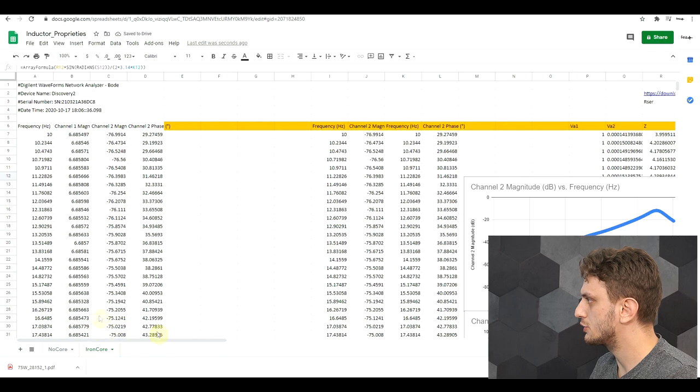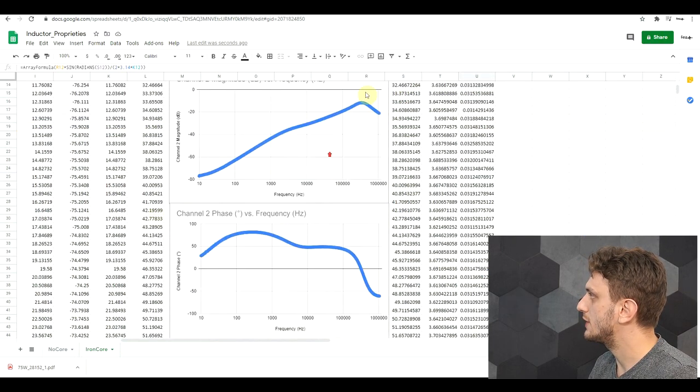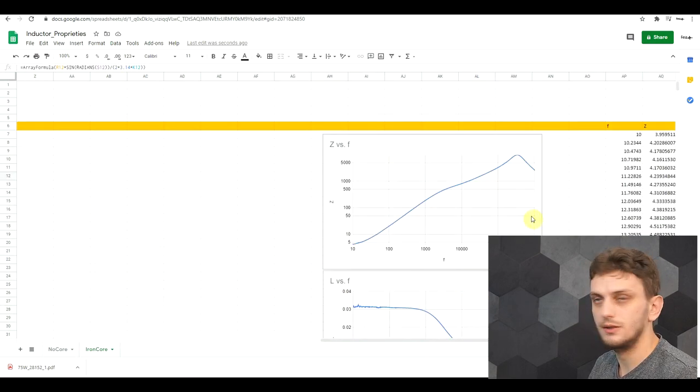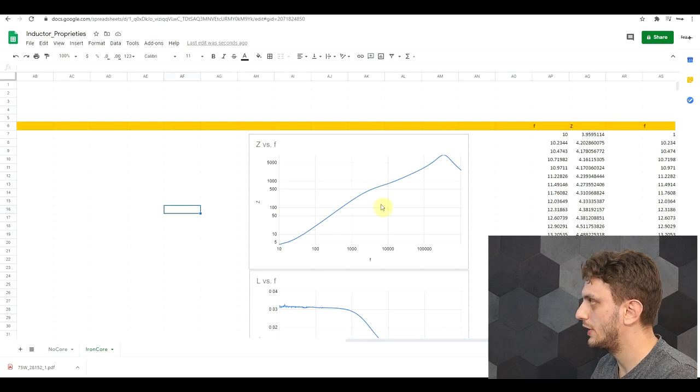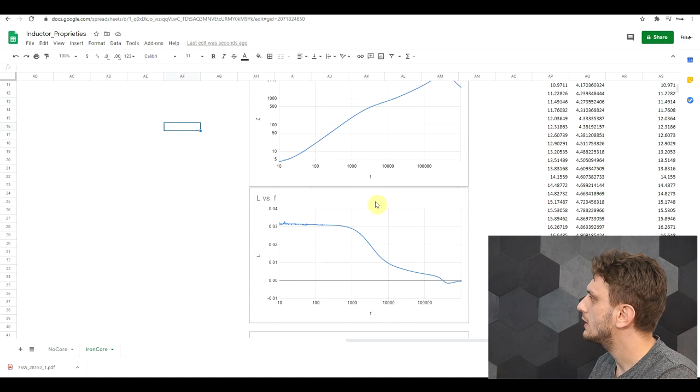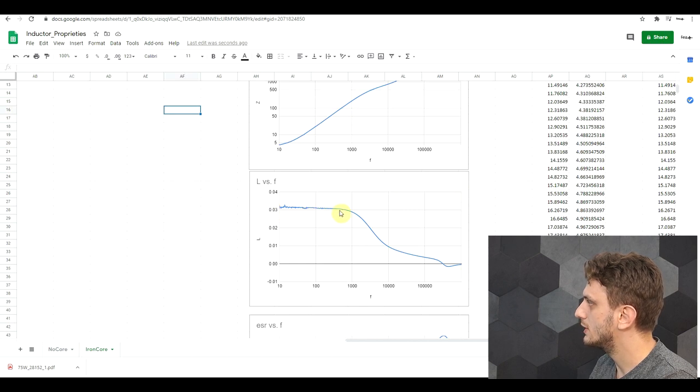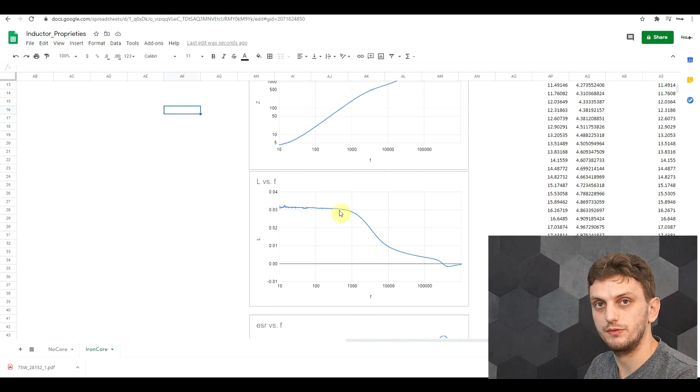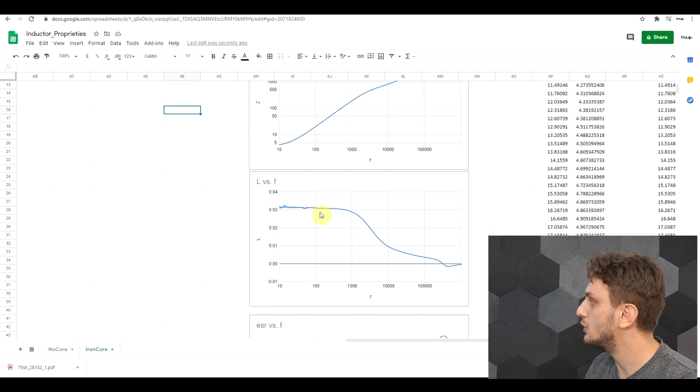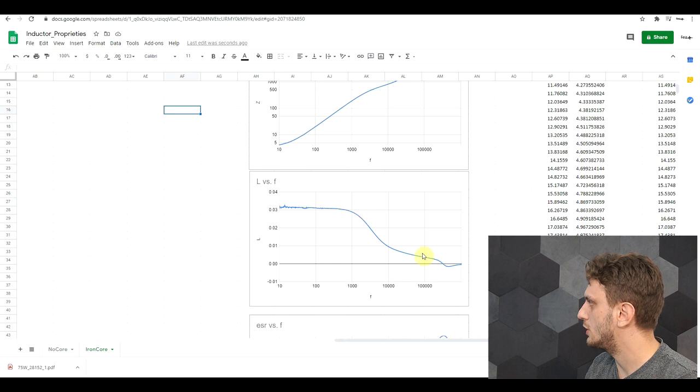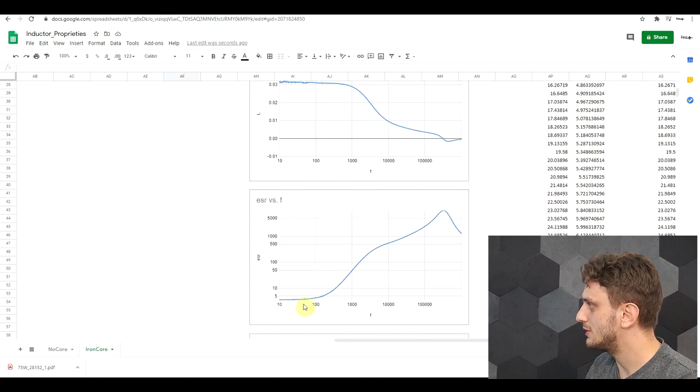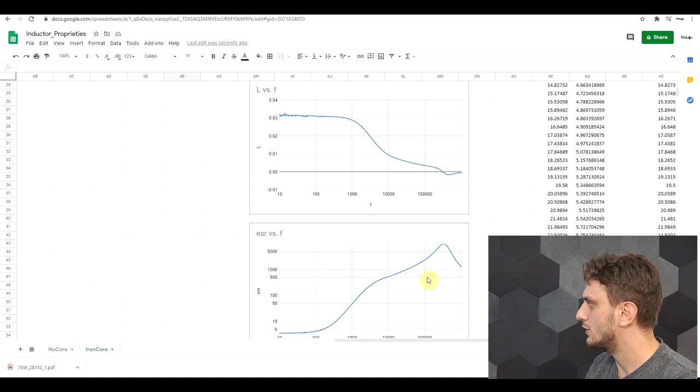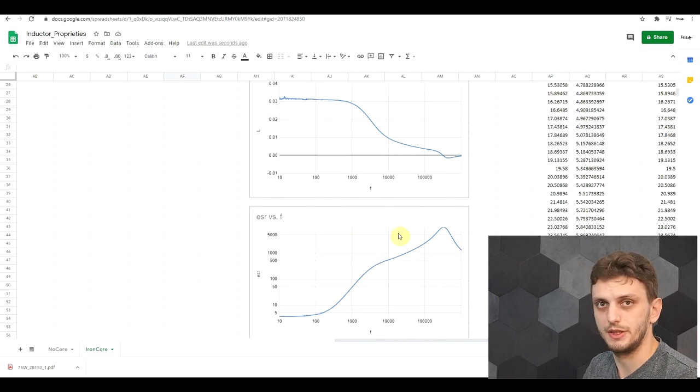So I created a new spreadsheet with the new data. Here we can see the graphs of the data that I just imported. And then if we move on to the process data. So we see this impedance varying just like we had our measurement. And now if we move on to the inductance, we see something's really strange. So we see our constant inductance much higher than before. So before it was 500 microhenry, this is 30 millihenry, so it's like 60 times more. But then after around 1 kilohertz it drops off. Now if we move on to the ESR, we see at low frequencies mainly the wire resistance, but then this increases. So as our inductance is falling, the ESR is rising, and it gets up to quite substantial values.